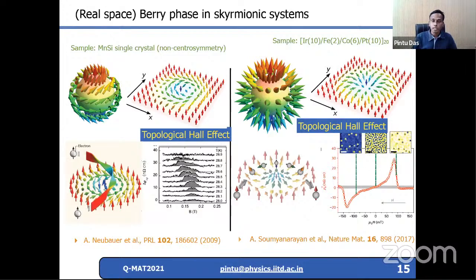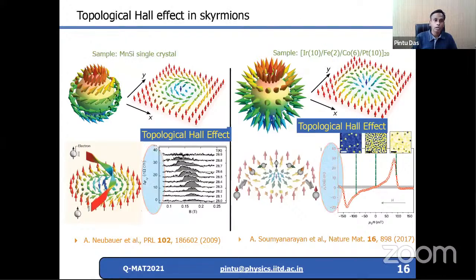So our interest is in understanding this topological Hall effect in a different system, and in addition, we wanted to look at the low frequency dynamics of carriers. I would like you to note that this topological Hall effect signal is very, very weak, of the order of a few tens of nanoohm centimeter for both single crystal bulk as well as for multilayer films. So you see that this is around 30-40 nanoohm centimeter of that order.